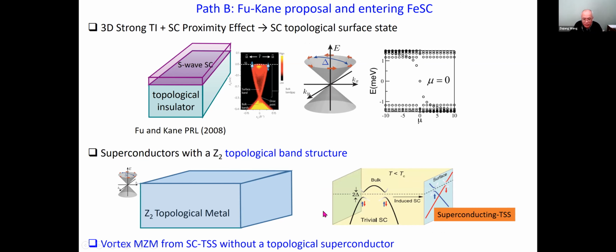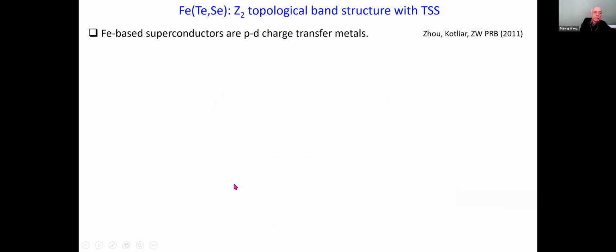So I want to emphasize that this is by no means a topological superconductor, not in the sense of the usual definition that we have for topological superconductor, to have a non-trivial topological invariant. It is not that. It is an s-wave superconductor, but the topological aspect comes from the band structure. Okay. Now, FTS really is such a candidate. It has a Z2 topological band structure.